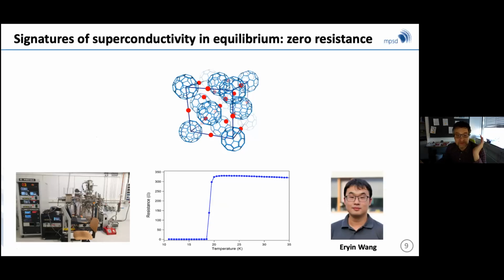Cesium and rubidium become superconducting at higher temperatures, but this is the material that we study. Superconductivity is manifested, as I mentioned before, by a number of DC properties, including the DC resistance, which, as I said, goes to exactly 0 below 19 Kelvin. These are samples that we've now learned how to grow ourselves in an MBE, and we now do experiments with thin films of C60 grown and developed by my postdoc Eryin Wang.